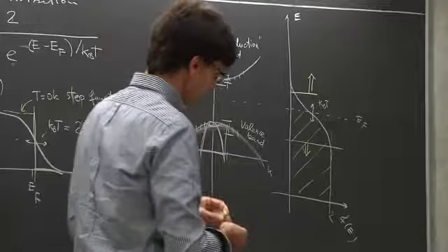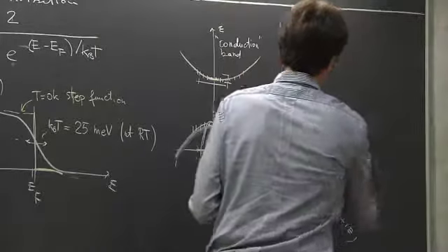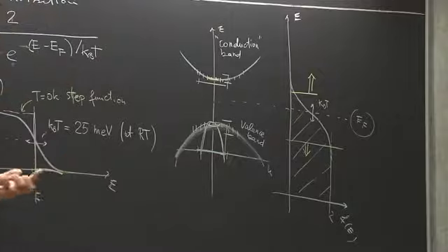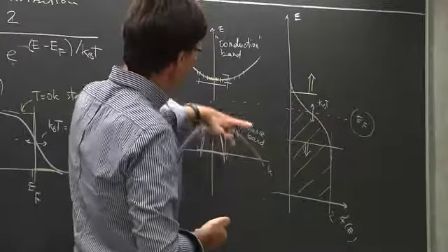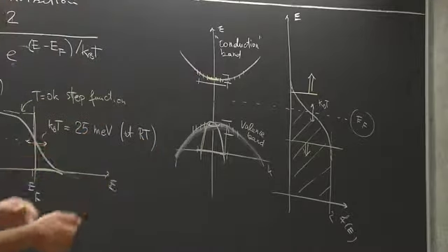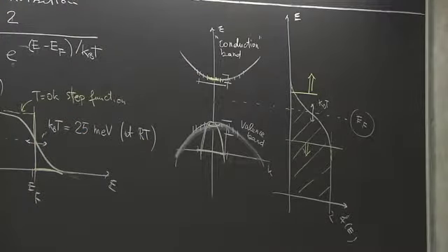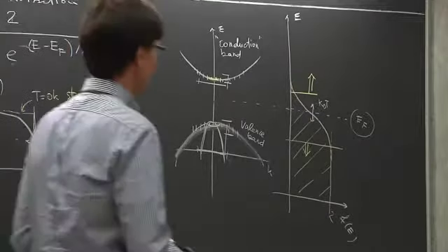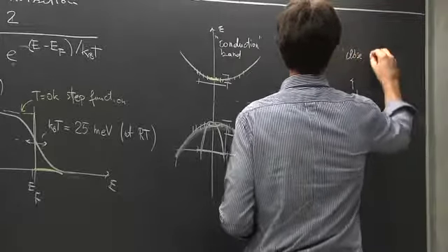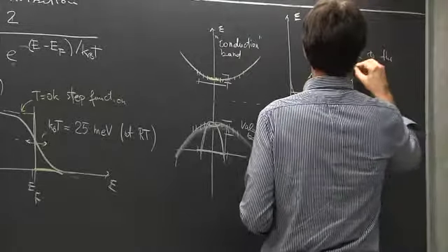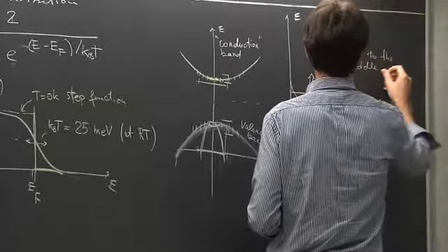So this is just a way to say that the position of the Fermi level is determined by charge neutrality, by the conservation of the number of electrons, but it is not necessarily located exactly at the middle of the gap because of the different shapes of the bands, in the valence and in the conduction part of the band structure. Okay, so this is close to the middle of the two, but not necessarily at the center.